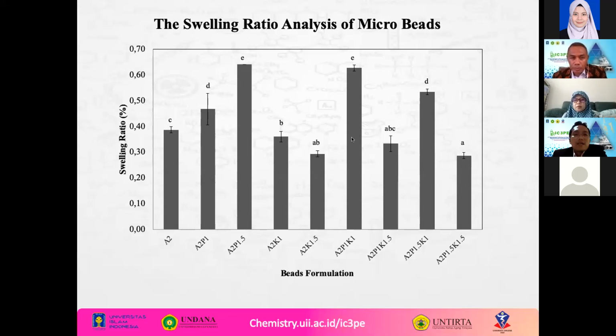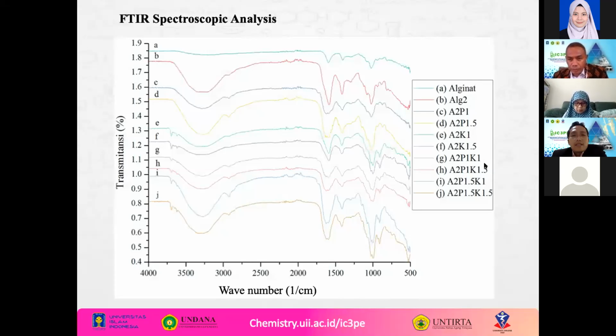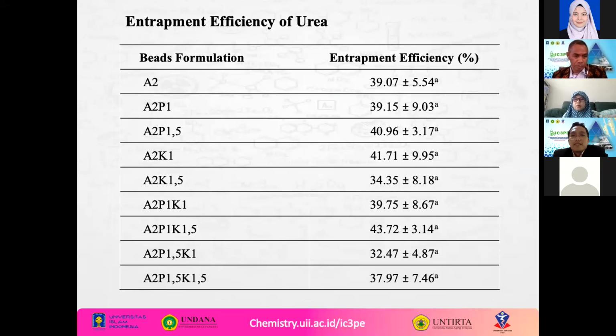This is the FTIR spectra of alginate, alginate starch, alginate kaolin, and alginate starch and kaolin. Maybe not a significant difference, only a shift of the peaks. And this is the urea entrapment efficiency. Actually, the addition of starch and kaolin did not change the entrapment efficiency. The efficiency of the entrapment of urea in the alginate beads is relatively the same, 32 to 43%. So the entrapment efficiency is not significantly different. Okay, two slides more.